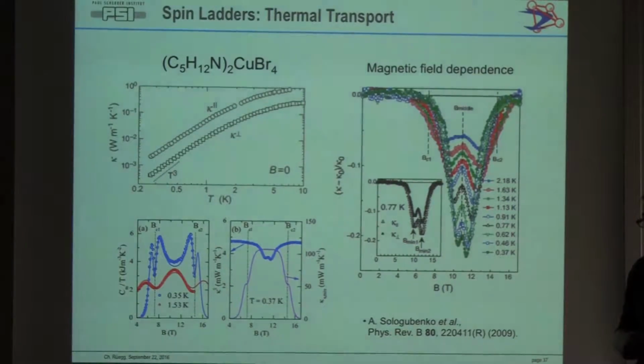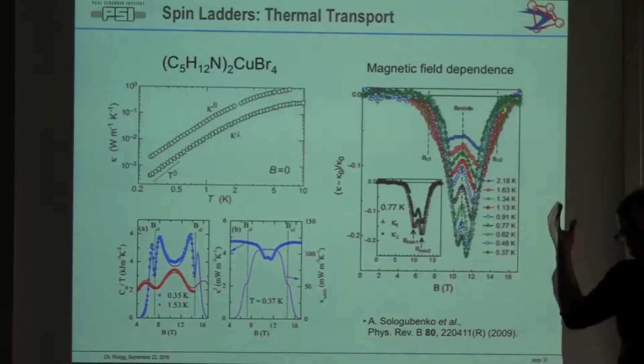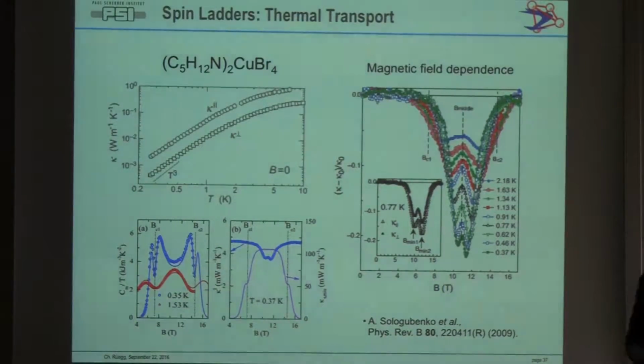So in terms of excitations, if this is true from, let's say, this paper from Bella Lake on potassium copper fluoride, you're in a regime where the temperature is mostly populating the spinons. There's nothing at low energies. Yes, so that's the transport story. We understand the magnons very well. There's no surprise in what the elementary excitations are. We can even measure the two-magnon states very nicely. The transport we tried, and that's the situation now.